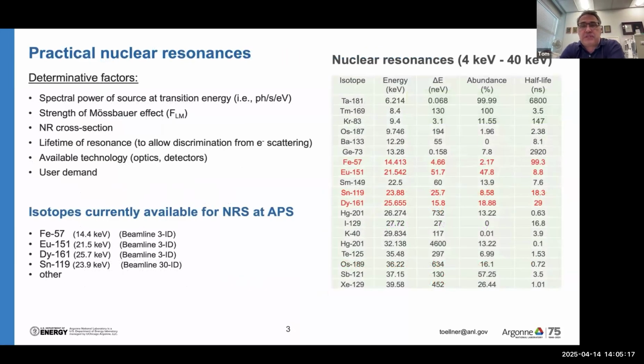So there are a number of nuclear resonances, say below 40 keV, where source strength is strong, but there are still a number of determinative factors that can limit their suitability. One, of course, is the strength of the Mössbauer effect. As one goes up in energy, the magnitude of the effect drops. Typically for very high energies, 60, 70, 80 keV, samples would have to be cooled cryogenically in order to measure a reasonable signal. This places some limitations on experimental environments. So that's something that always comes into play.